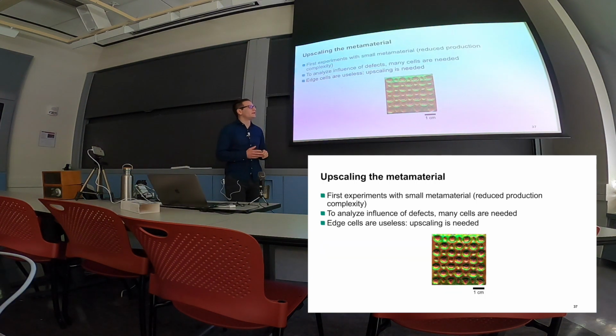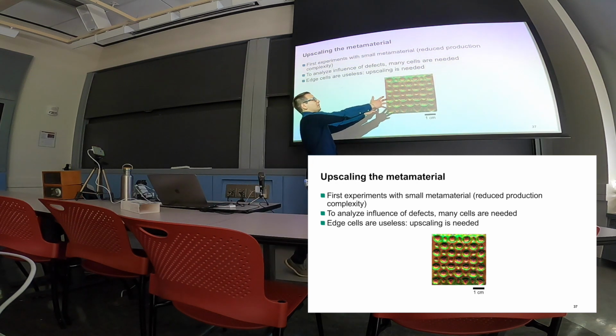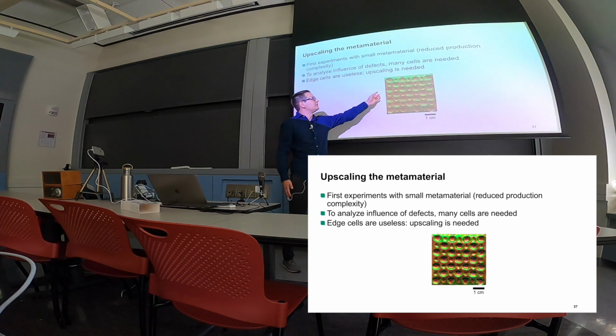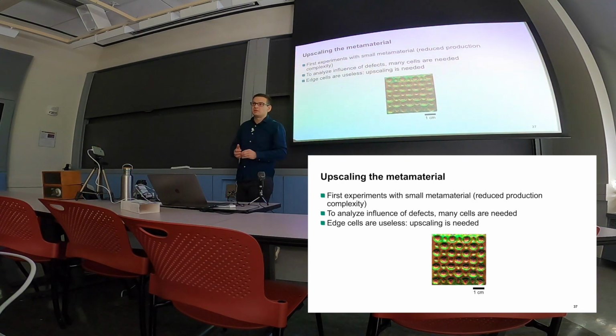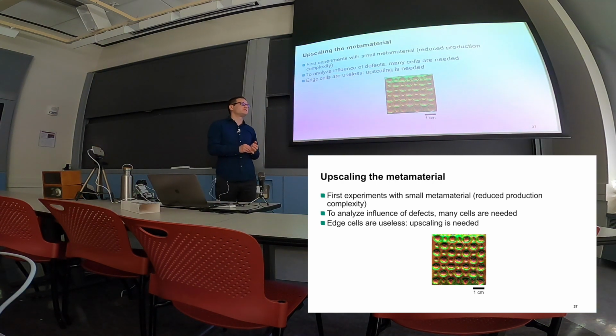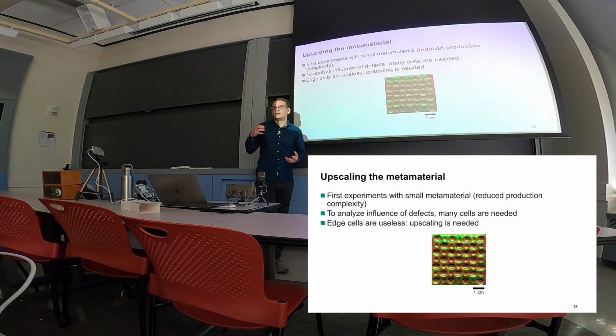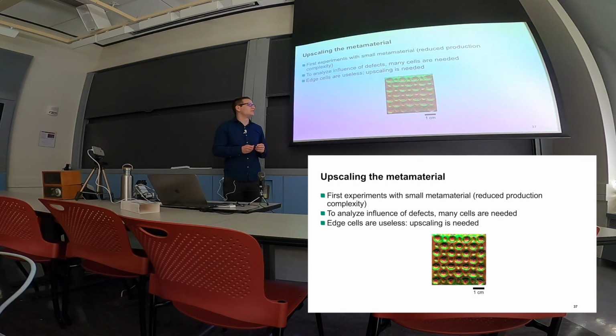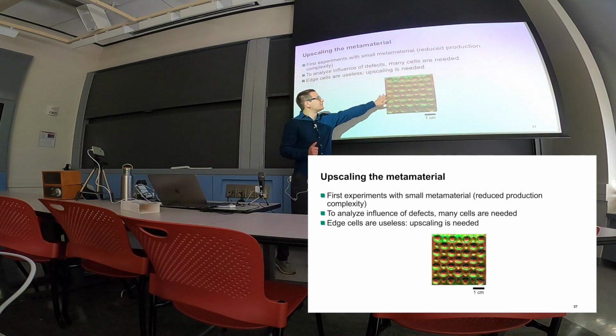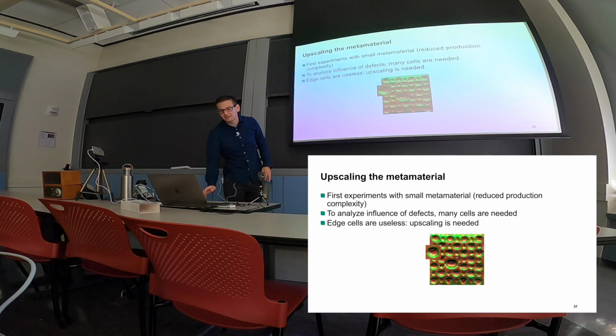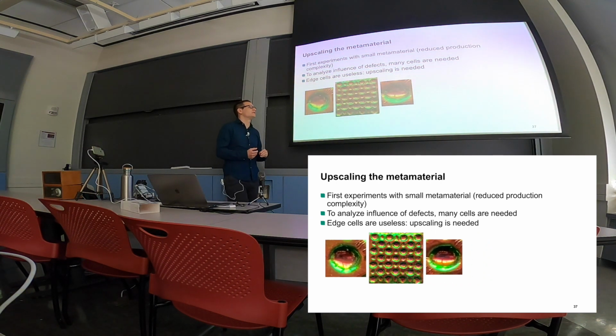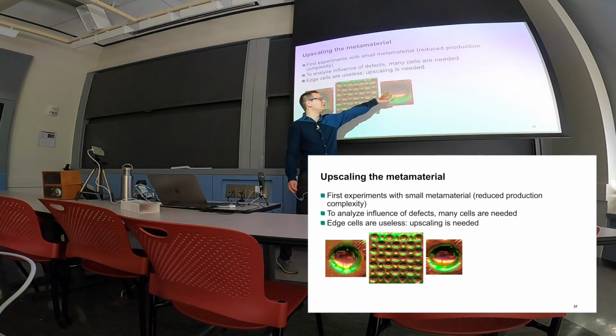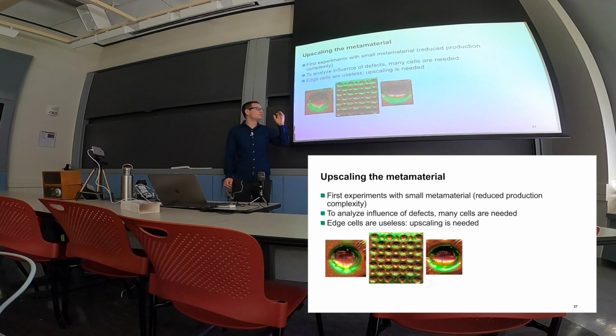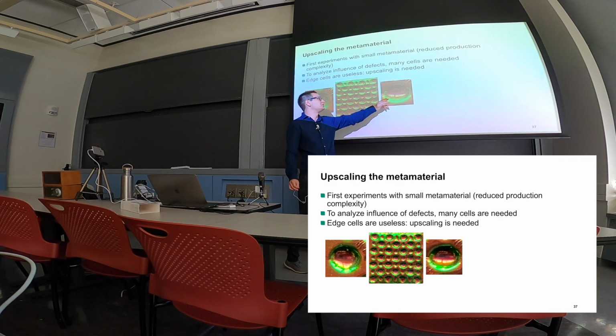And to analyze how the overall network behaves, I definitely needed to have a bigger network than the one over here, because what we can see is that I just have a few cells in that network, and as mentioned, the production of that metamaterial, especially the upscaling, was extremely difficult due to the high aspect ratio of the holes inside of that material. And we can see that this network over here consists of probably 49 cells, and one more bigger problem that I figured out when playing around with that material is that if we have a look at the edge cells, which we can see here on the left side compared to the middle cells, what we see on the right side, by even applying just a slight vacuum, there is a round-shaped cell on the edge and a more, let's say, cylindrical-shaped cell in the middle part.